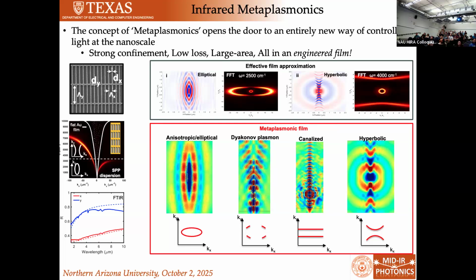This gives us extremely strong confinement of our optical modes. As I was saying at the beginning of my talk, a typical mid-IR detector is 8 microns thick to absorb long wave infrared light and get a reasonable signal. You pay huge penalties for that in terms of growth time and the challenges of growing a heterostructured material that thick. Here you have an optical resonator that is relatively low loss and confines 10 micron light down into a range of 30, 40 nanometers.